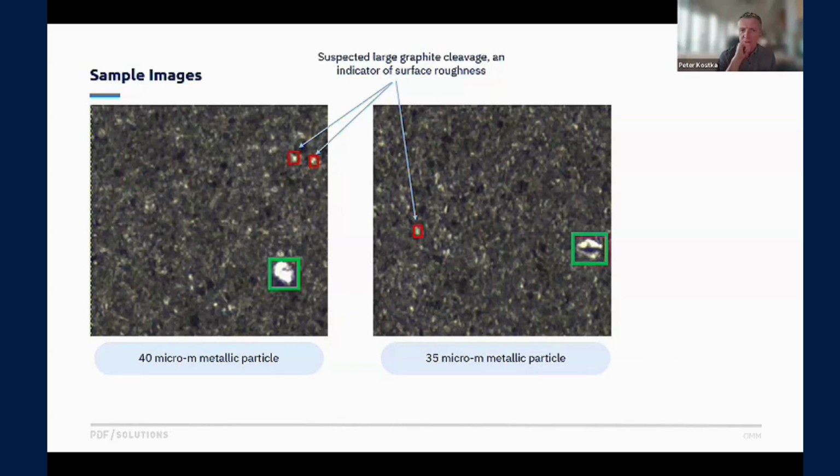So to kind of close the loop on that question, yeah, we could. We're tracking position, so we could stop the line and cut this little piece out, ship it over to SEM, and then spend however much time trying to find it. It's always a little bit tricky to get within that final 100 microns. But this is definitely not copper, just based on the color. Does that make sense?